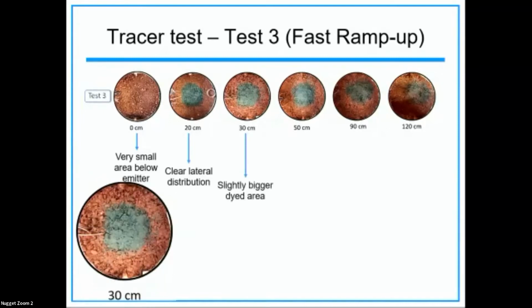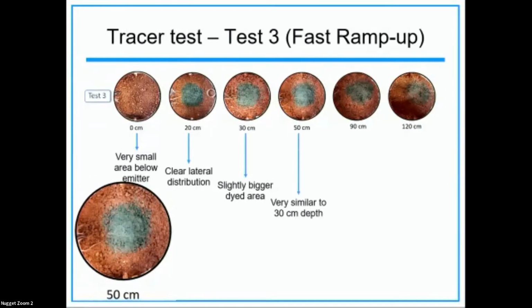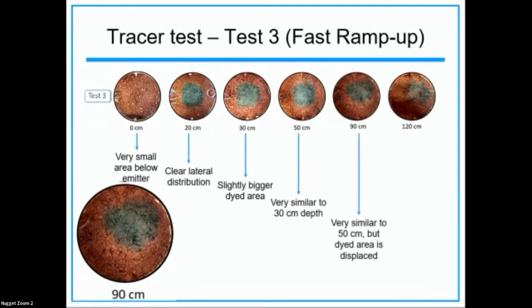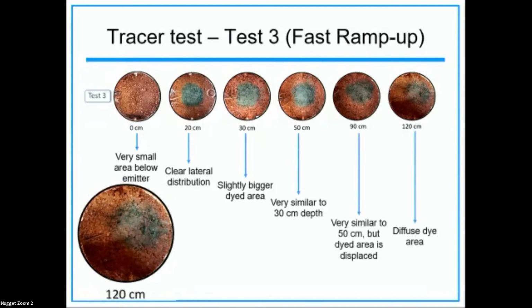And again, we see similar patterns, but it's not as dark of a blue as we saw in test number 2, which is the slow ramp up. And so by the time we get to the bottom, it's a little bit moving around, and it's not quite as uniform as what we saw in the slow ramp up.